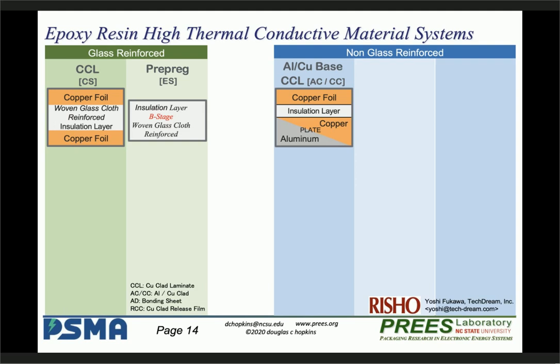Before, in the previous slides, Mitsubishi did insulated metal base plate, IMB. This is the traditional IMS. IMS has been around for many years. And so it's copper foil you can get of different thicknesses, up to like 20 mil thick. Insulation layers, we'll show in a second what the layers are. And then the thick base plate or copper plate at the bottom. Tell me what cost you want, what thermal performance you want. So this is a whole material system we look at.